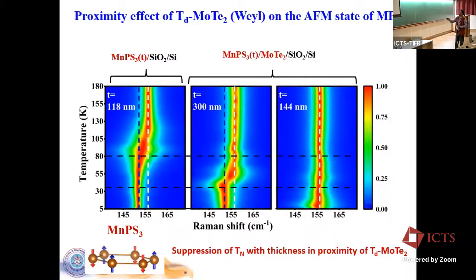Okay. Now, if we reduce the thickness to about half of it, we are not able to see the transition. Our lowest temperature was 5 Kelvin. So we believe, even if the transition is happening, it could be below 5K or just around 5K. All right. And going below this thickness was not useful. We did that, of course, we couldn't see anything. All right. So at least the first observations tell us that if we put MnPS3 on something like MoTe2, there's something happening. Some engineering is happening in the magnetic interactions.